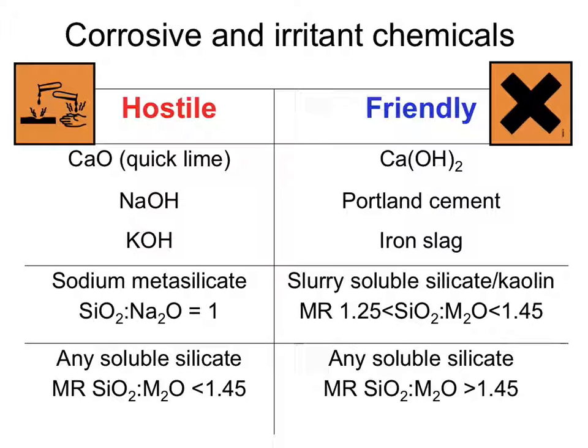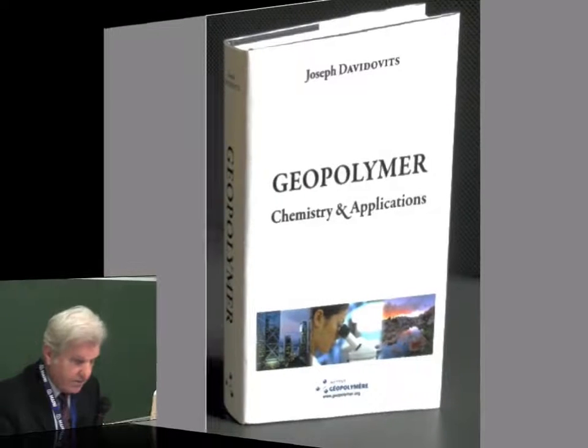In the hostile column, you have quicklime, NaOH, KOH, sodium metasilicate with SiO2:Na2O ratio 1, any soluble silicate with a molar ratio less than 1.45. And in the friendly column, you get slaked lime, Portland cement, iron slag, a slurry that has a molar ratio between 1.25 and 1.45 that contains kaolin, because kaolin is a protective material, and of course any soluble silicate with a SiO2:M2O ratio higher than 1.45. This is very thoroughly explained in one chapter of my book.